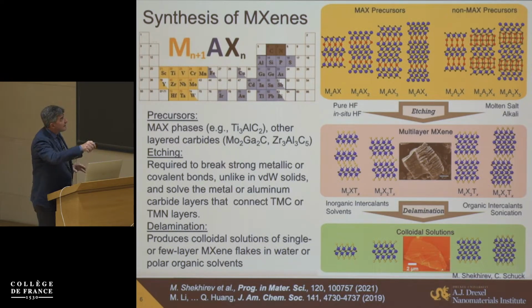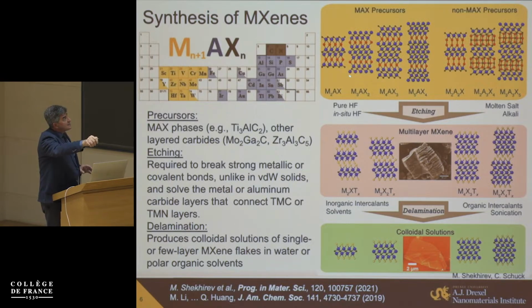Typically, they are made by taking so-called MAX phases. Those are layered ceramics like this one, layers of carbides and nitrides separated by monatomic layers of A element, one of the elements from this group. Or layered carbides like zirconium aluminum carbide, hafnium aluminum carbide, other materials like Mo2GaC, basically layered ceramics.